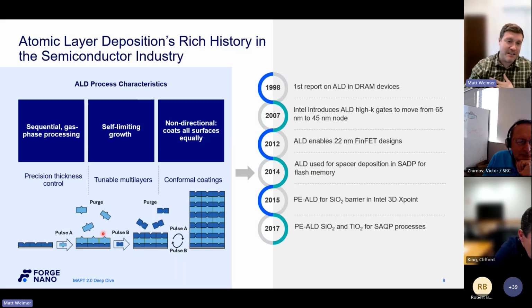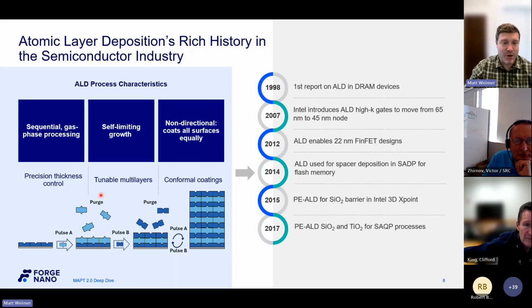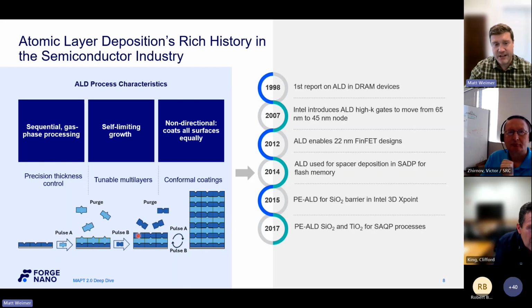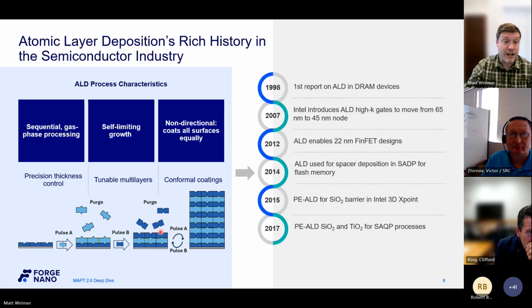As a chemist, this little Lego block schematic hurts my soul because it doesn't show you the reaction byproducts, which can be quite important. So those also need to be removed. That purge part of the cycle actually takes a bit of time, which is one of the reasons that ALD is so slow. And then you have to introduce a complementary precursor, these blue bow ties here, that again react only with those blue spikes. And then you get that same monolayer coverage. Typically, this is some sort of oxygen source or nitrogen source. So if you think about this as water, it's really hard to imagine water growing on top of water unless you're doing condensation, which we're hot enough, so we don't have to worry about that. We've now done one cycle of ALD. We get a digital amount of film, so the same amount of film, usually on the scale of angstroms or even sub-angstroms.